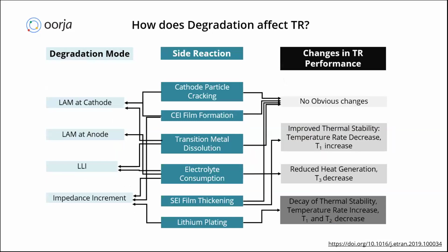This is the diagram shown in the slide, which will give you a fair understanding of what types of degradation modes are present in the cell and how they affect the thermal runaway performance of the cell. All in all, because of the degradation, the thermal stability of the cell reduces, because of which the temperature rise rate increases. And the next challenge is that T1 and T2, when the self-heating reactions start and the thermal runaway gets triggered, both temperatures come down, and because of that the thermal runaway can get initiated at an earlier stage than, let's say, around 90 degrees or around 140°C itself.